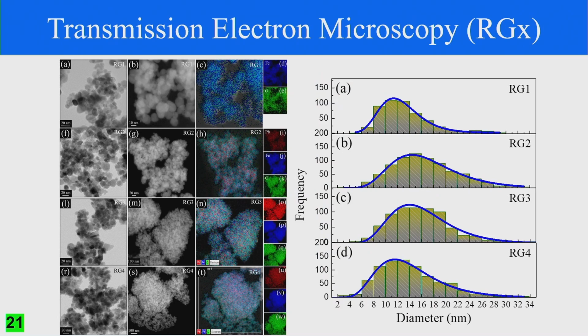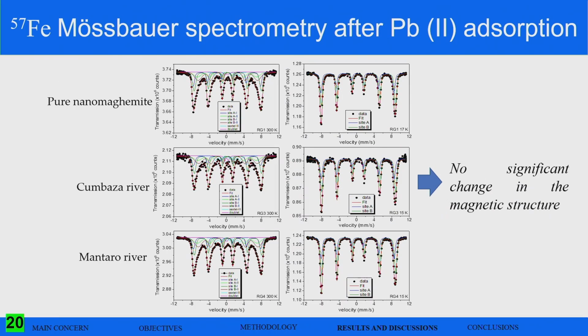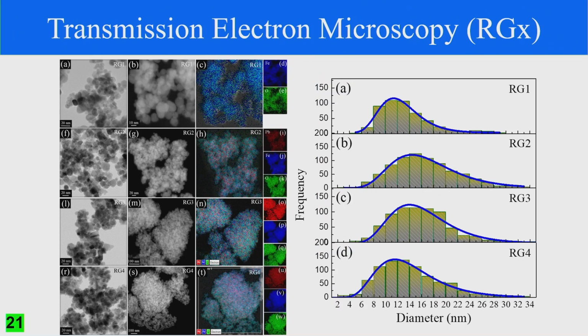So to confirm that we have a homogeneous particle size distribution after the adsorption of lead, and in agreement with the zero-field Mossbauer spectrometry, we performed the particle size distribution, and we see that the particles are not bigger than 20 nanometers, in agreement with the co-precipitation method, and of course with the control pure nanomaghemite.